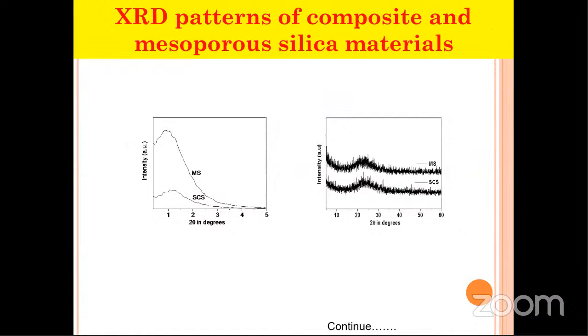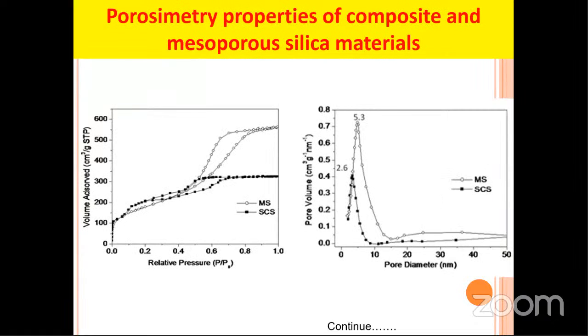So this material has been characterized by various analytical techniques. From low angle XRD, you can see that the MS material has more porosity compared to the sulfonated carbon silica composite material. Wide angle XRD pattern shows that the material is amorphous in nature. From nitrogen adsorption-desorption isotherm, we have a type 4 isotherm, which is related to mesoporous material. The average pore diameter for SCS material is 2.6 nanometer. For MS material, mesoporous silica material, we have 5.3 nanometer.